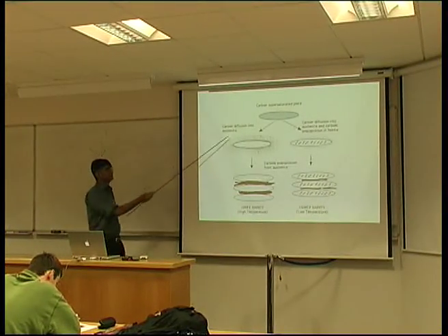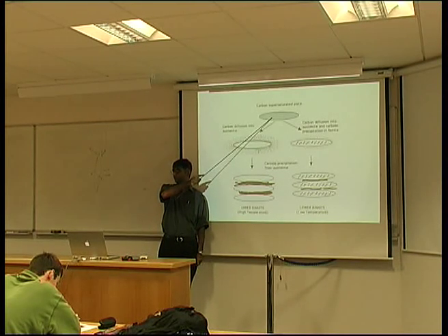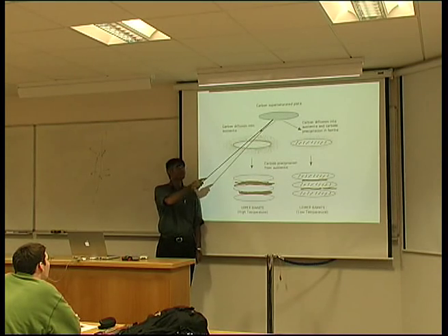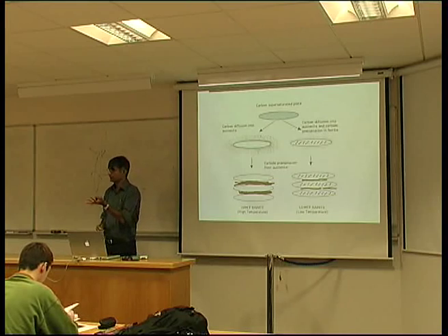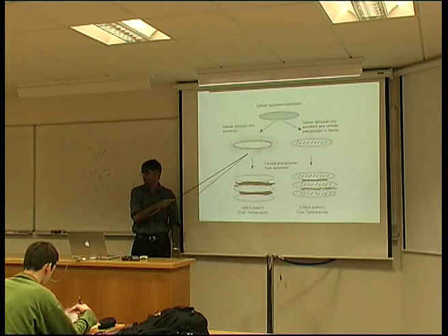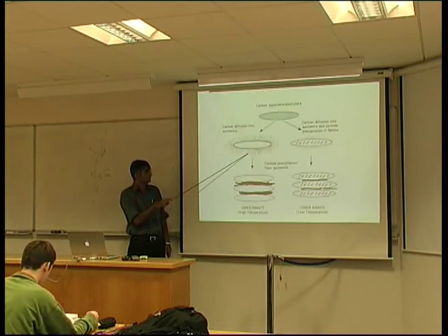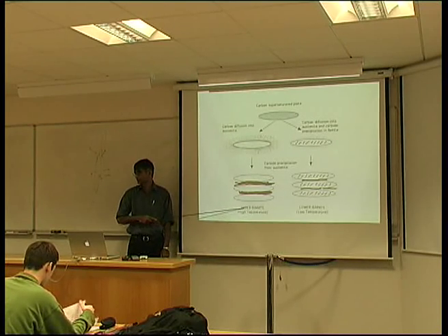Okay, so let's imagine that bainite forms exactly like martensite. There is absolutely no diffusion of carbon, silicon, or whatever. But we are forming this at a relatively high temperature, so it will temper itself. In other words, the carbon will escape from the plate of bainite because it doesn't want to be there. And then it will precipitate as cementite. That would give us our upper bainite microstructure.